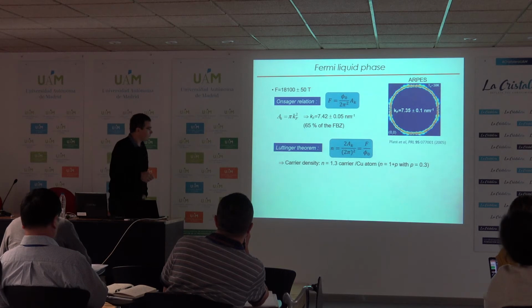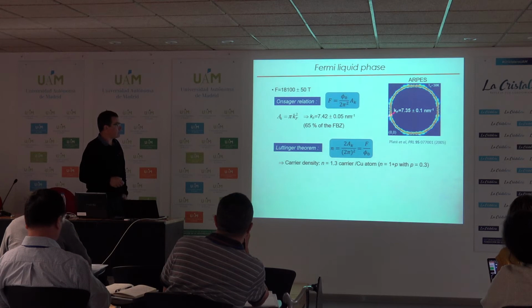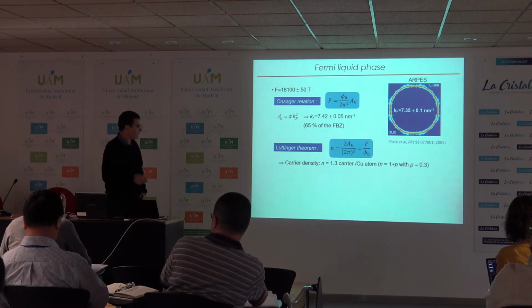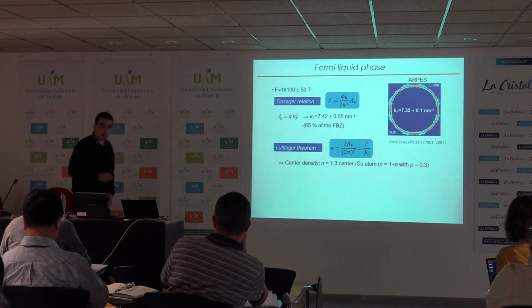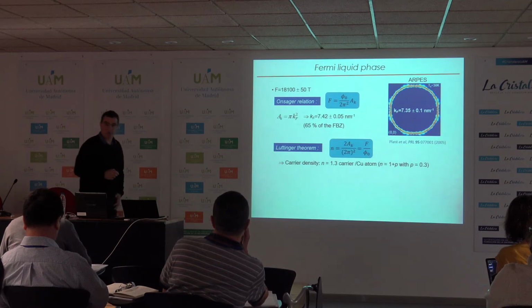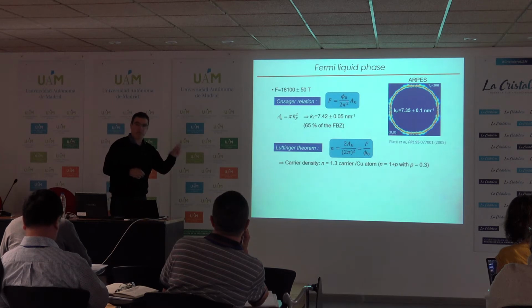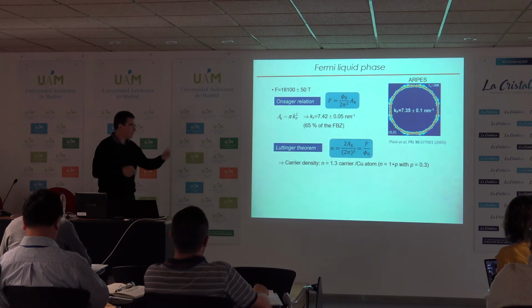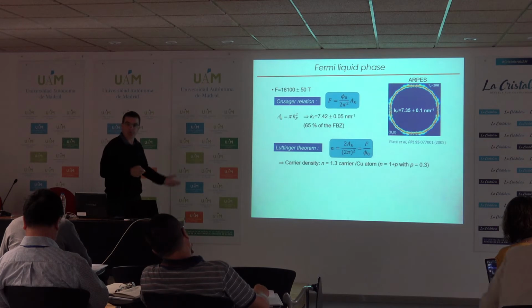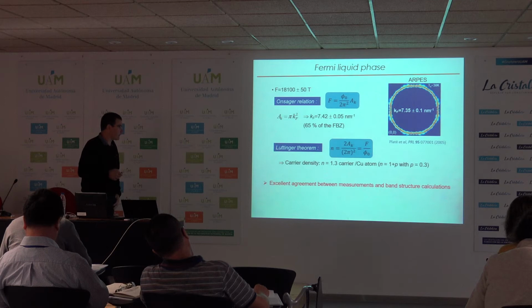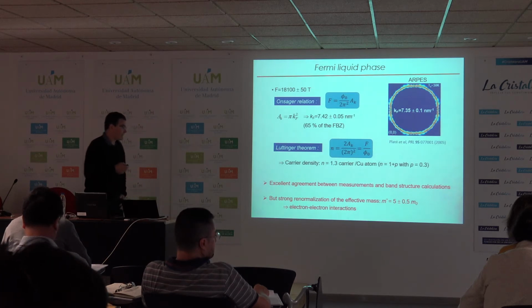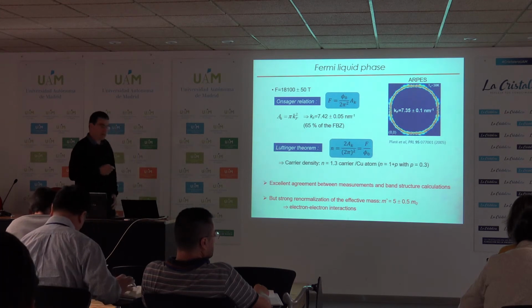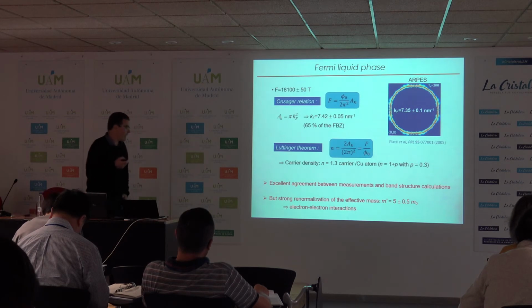Now in 2D, you have the Luttinger theorem, which tells you that the density of carriers is directly related to the area of the Fermi surface, meaning to the frequency of the oscillation. If you put in the numbers, you find a carrier density of 1.3 carriers per copper atom, which is exactly what is predicted by band structure calculation. I recall that the parent compounds are half-filled metals, so you expect one electron per copper for the parent compound, and this particular sample has a doping of 30%, meaning you have 1 plus 0.3 carriers per copper atom. So this measurement shows an excellent agreement between quantum oscillation, ARPES, Hall effect measurement and band structure calculation. But we found an effective mass of around 5 times the free electron mass, and this shows that even on the strongly overdoped side, you still have strong electron-electron interaction.